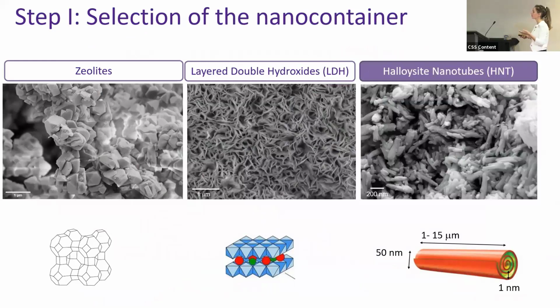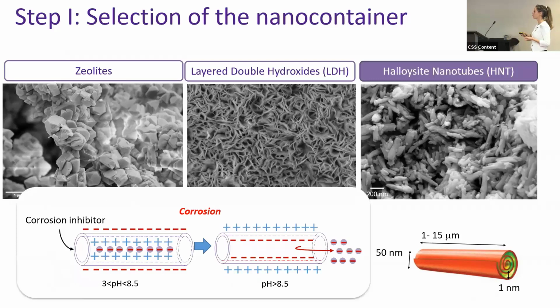They can either have 3D structures, layered structures, or tubular structures, where they will host these corrosion inhibitors. For this work, we've selected halloysite nanotubes, which are natural clays formed by 2 layers of aluminosilicates arranged in a hollow tubular shape. At neutral pH, the nanotubes are negatively charged on the outside and positively charged in the inner lumen. This means that they can host negatively charged corrosion inhibitors and will remain encapsulated because they will be attracted by electrostatic interactions.